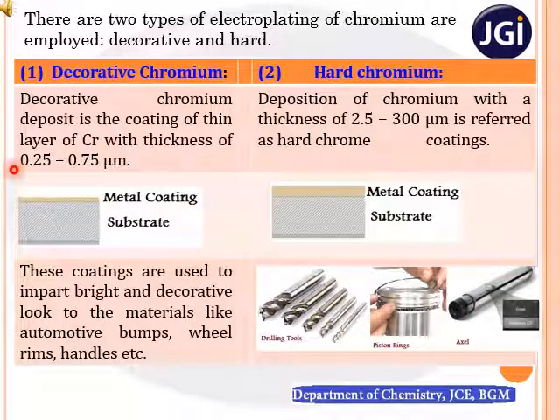It means that depending upon our requirement, we can coat the chromium. If the coating of chromium is only for decorative purposes, then we can restrict its thickness between 0.25 micrometer to 0.75 micrometer, and hence this type of deposition is decorative chromium. Similarly, if our requirement is to improve surface properties like wear and tear resistance, scratch resistance, and corrosion resistance, in such cases we need to coat the chromium metal with a greater thickness. That maximum thickness is up to 300 micrometer.